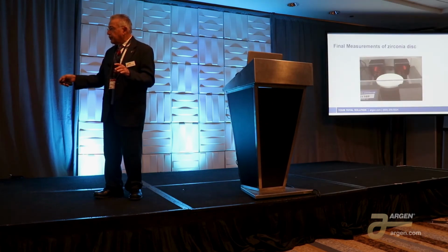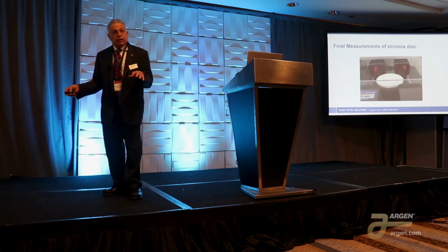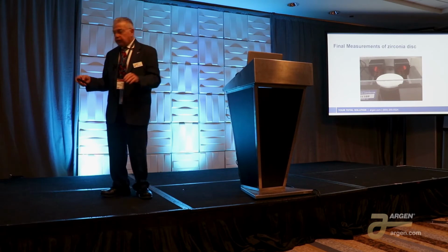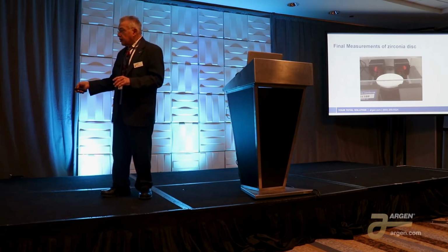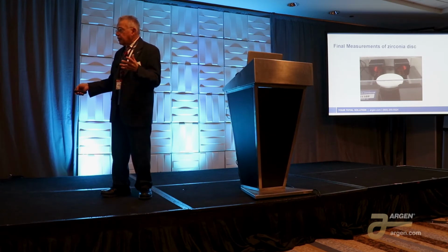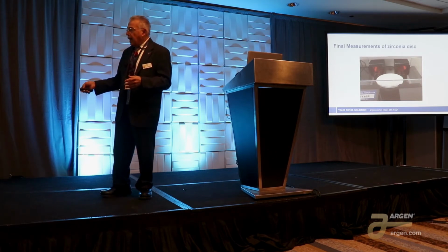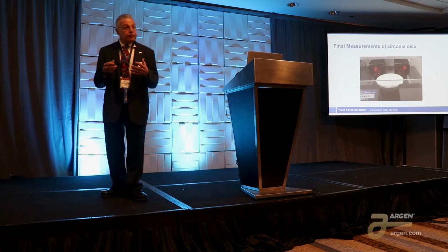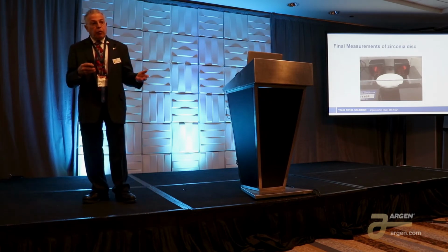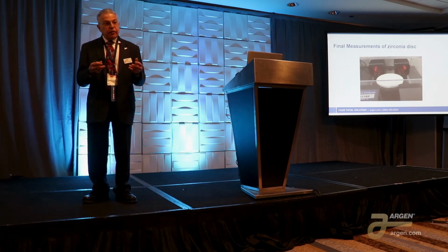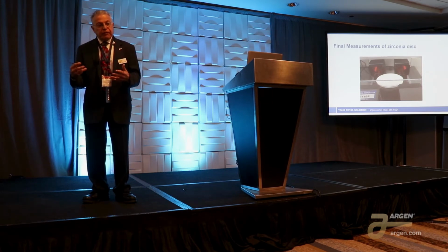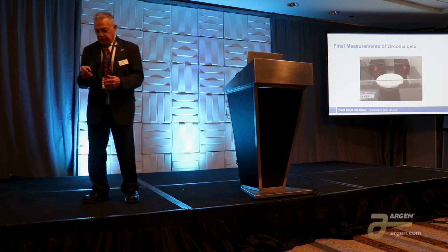There's a station to the left where there's a weighing station. It goes right into the computer. The measurements are taken in less than 2 seconds. And we measure the height, the width, the diameter of the top, diameter of the middle, and the diameter of the bottom. And that calculates the volume. From there, we combine that with the weight, we calculate the density. So this is the density of this piece. We know what the final density is going to be, so we can calculate the shrinkage rate.